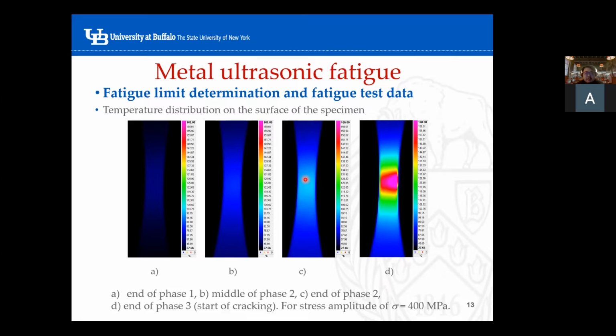So the temperature difference is actually already very high for the ultrasonic vibration fatigue, even though it is only in phase 2. The temperature difference between the gauge section and grip section is already around 80 to 100 Kelvin in the ultrasonic vibration fatigue. It is very large compared to a conventional high cycle fatigue.